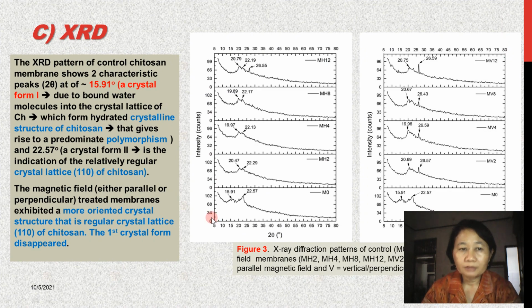For X-ray diffraction, the X-ray pattern of the control Chitosan membrane shows two characteristic peaks at 2 theta. One is around 15.91 degrees, that is crystal form 1, due to the bound water molecules in the crystal lattice of Chitosan, which form a hydrated crystalline structure of Chitosan that gives rise to a predominant polymorphism. And the second peak is at 2 theta around 22.57 degrees. That is crystal form 2, the indication of the relatively regular crystal lattice 110 of the Chitosan.